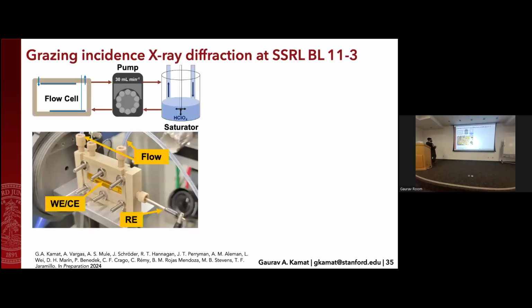So in order to study this, we used a technique called grazing incidence X-ray diffraction at the Stanford Synchrotron Radiation Light Source. Essentially, it's one of the world's brightest sources of light. It produces X-rays at a specific energy that you choose, and you can put them into your system in various ways to understand different dynamic phenomena. This cell that I've shown here has a working and a counter electrode opposite each other, and it has little windows that you can shoot the X-rays through in order to measure specifically the surface if you align everything just right.